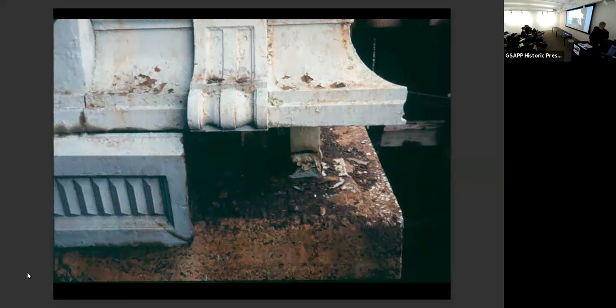All right. Is there a crack on that? There's a crack there in the corner, and then the other piece cracked off, and you see, in fact, that was one piece. You can see the vertical crack there. So that corner, and that corner also cracks. So if it's cracked or broken, it's cast iron. If it's pack rusted, it's steel.